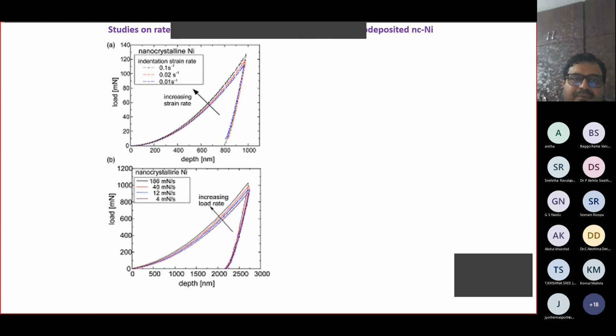And I'll come to this part later. That is the variation of mechanical properties based on the strain rate using nano indentation. This is a sample which was made using electrodeposition. This is a nanocrystalline nickel. As you increase the loading rate, you see a change in the behavior here. And yeah, I'll come back to this part later.